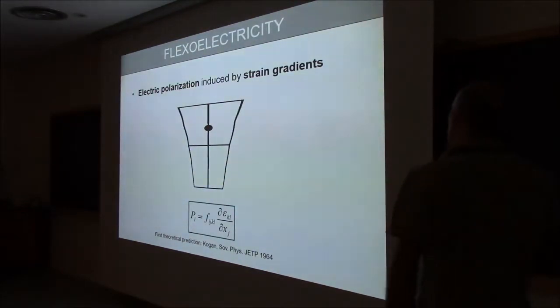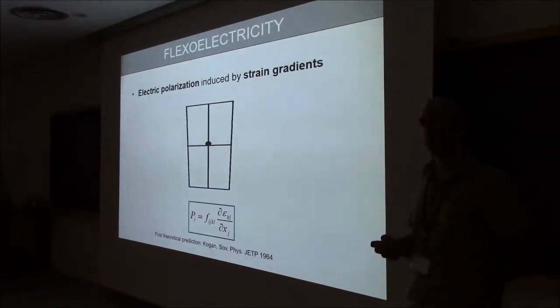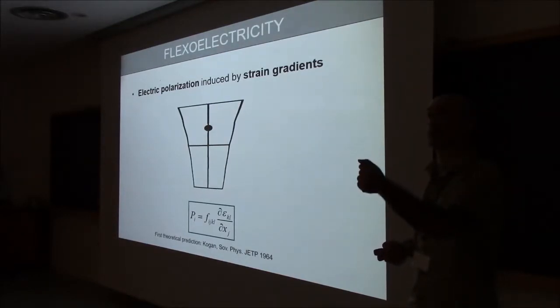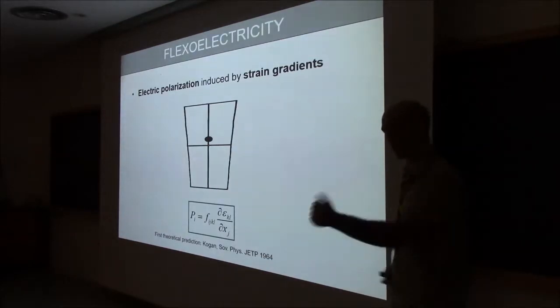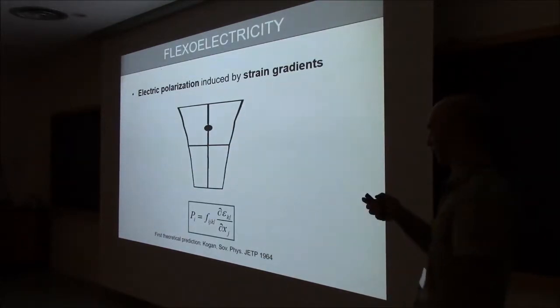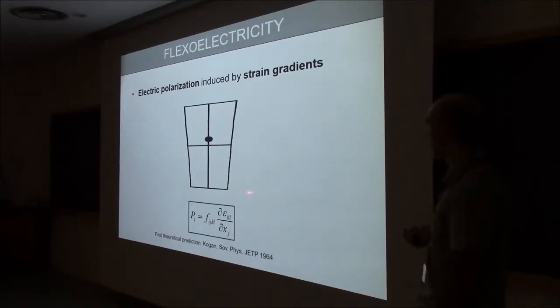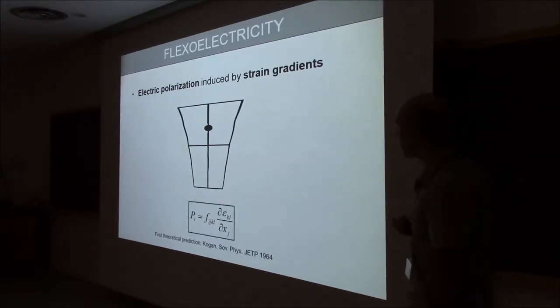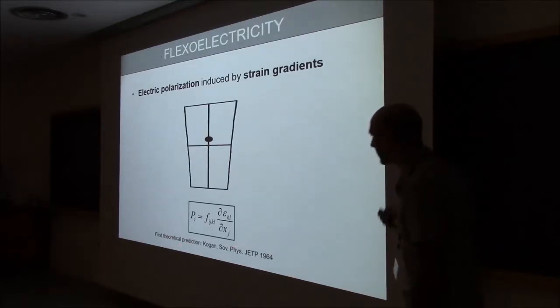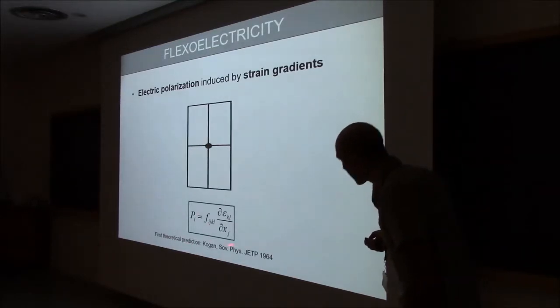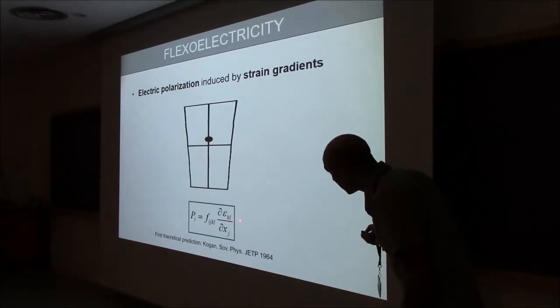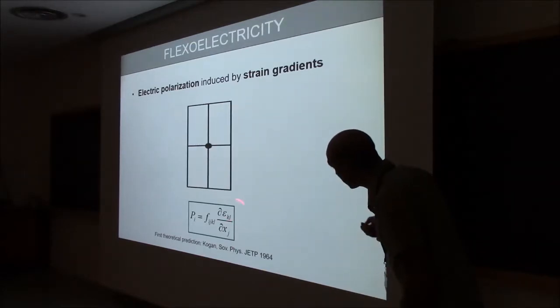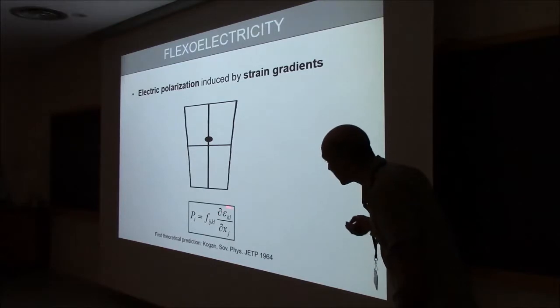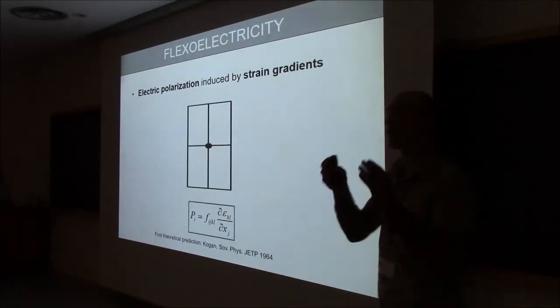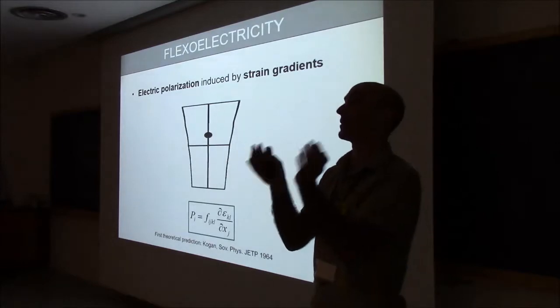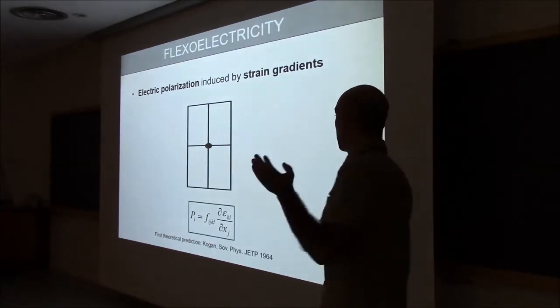And if you want to think of it in another way, it's a bit like squeezing the toothpaste out of the toothpaste tube, right? You squeeze the bottom, toothpaste comes up. That's more or less what happens. Okay, so this is a cartoon picture. This is the more exact mathematical definition, the polarization given to you by a strain gradient. Strain is a second-rank tensor. The gradient turns this into a third-rank tensor, which means that this is an odd parity tensor. That means that the strain gradient by itself breaks centrosymmetry.